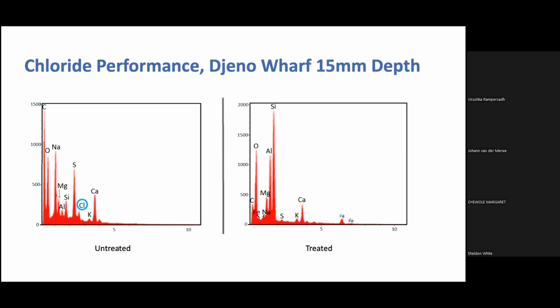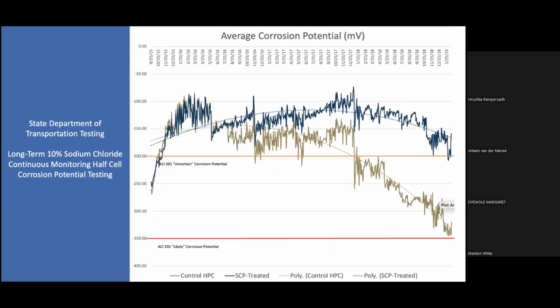I think around 30 cores were taken out of the project. They were then able to do some calculations on diffusion rate, et cetera, apparent chloride diffusion rate. We were able to show that the life expectancy of the untreated concrete was around 15 years. The life expectancy of the treated section was somewhere in the neighborhood of 32, 33 years, if I remember correctly. So you had about double the life expectancy from the treated concrete.